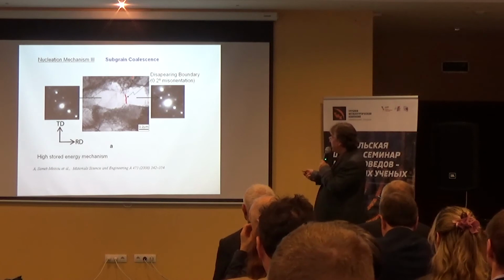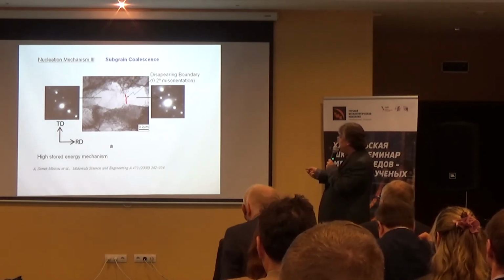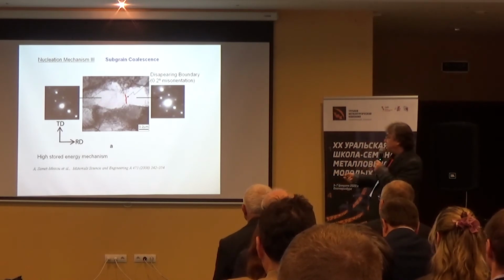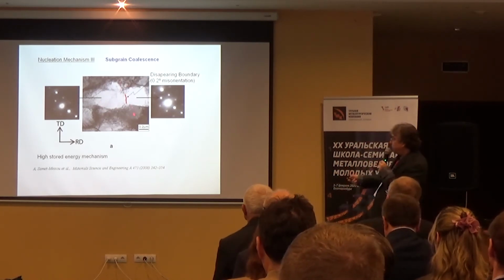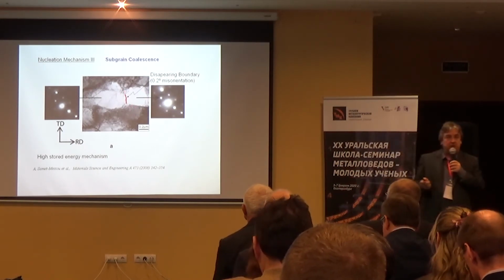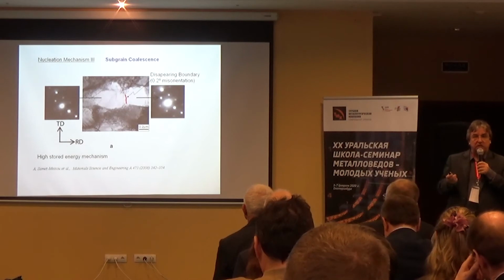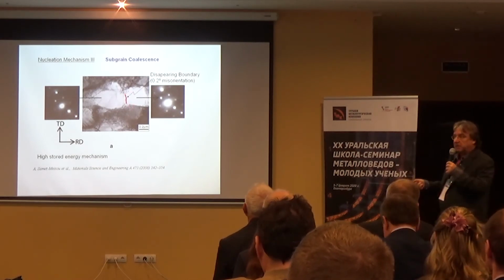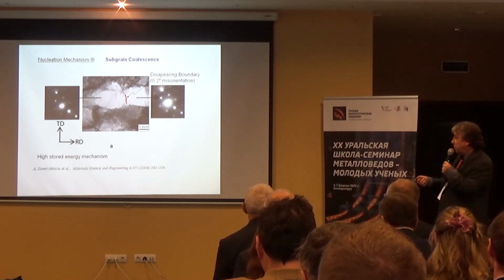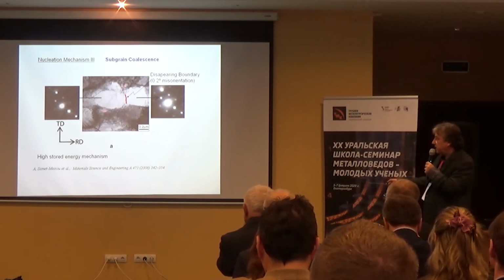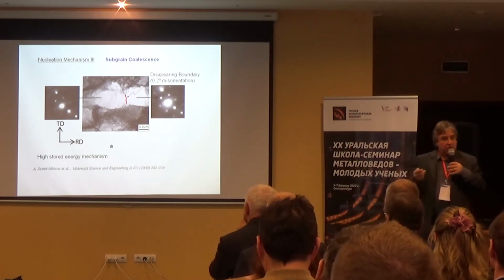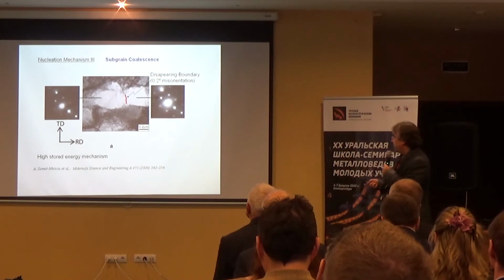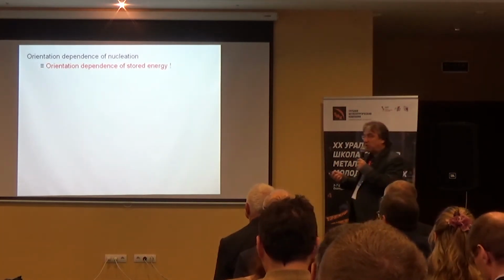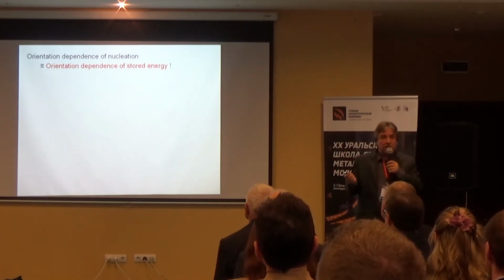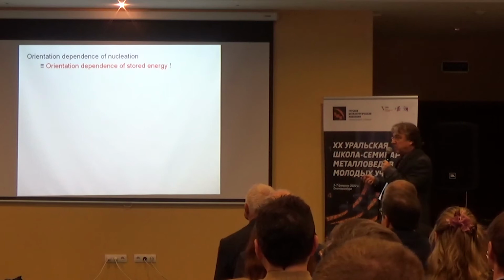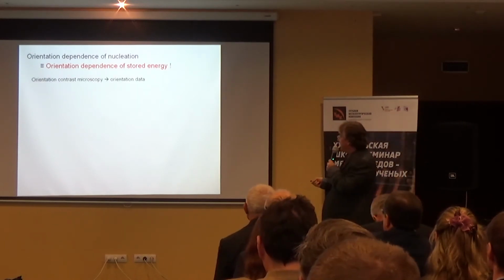Then you also have another mechanism which is subgrain coalescence. You have two cells, in fact two subgrains which are separated by a subboundary, which normally has a small misorientation, and by diffusion effects of dislocation climb, this dislocation boundary will disappear and this merges into one large subgrain which then starts growing into the deformed matrix. Okay, so all these mechanisms, as I said, are orientation dependent. Why? Because the stored energy is dependent on the orientation.